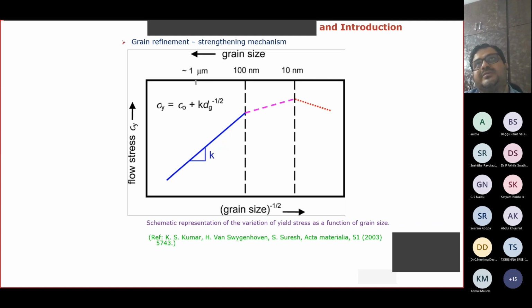Therefore, in conventional coarse grain materials, where the average grain size is tens of microns, dislocations, which are line defects or one-dimensional defects, whatever you call them, are the main controllers of plastic deformation. So once you understand the dislocation movement in these materials, then you have a full understanding of how to design stronger as well as harder materials. And the other part here: if you see the flow stress or yield strength on the y-axis and grain size raised to minus half on the x-axis, you see that up to 100 nanometers we have one slope, that is k shown here, and these are the conventional materials.